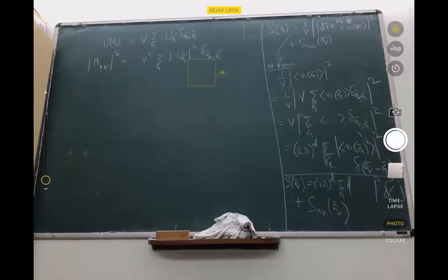If there is anyone who has some idea about this, just speak up. Correlations between fluctuations of the density. Right. So if you understand that, then what is S_NN(Q) in an ideal crystal? It should be 0 because there should be no fluctuations. Absolutely. So it is 0 in an ideal crystal. So then S(Q) has contribution only from the first term.